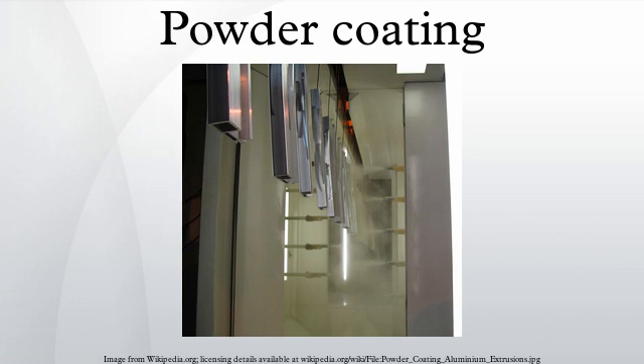Electrostatic fluidized bed coating. Electrostatic fluidized bed application uses the same fluidizing technique as the conventional fluidized bed dip process but with much less powder depth in the bed. An electrostatic charging medium is placed inside the bed so that the powder material becomes charged as the fluidizing air lifts it up. Charged particles of powder move upward and form a cloud of charged powder above the fluid bed. When a grounded part is passed through the charged cloud, the particles will be attracted to its surface. The parts are not preheated as they are for the conventional fluidized bed dip process.